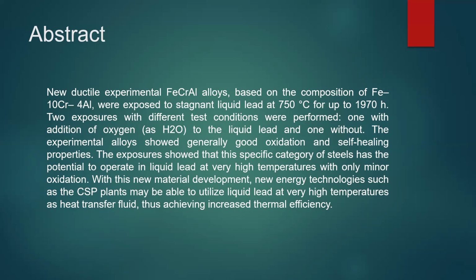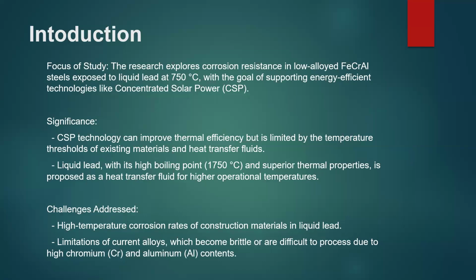The experimental alloy showed generally good oxidation and self-healing properties. The exposure showed that this specific category of steel has the potential to operate in liquid lead at very high temperatures with only minor oxidation. With this new material development, new energy technologies such as CSP plants may be able to utilize liquid lead at very high temperature as a heat transfer fluid, thus achieving increased thermal efficiency.